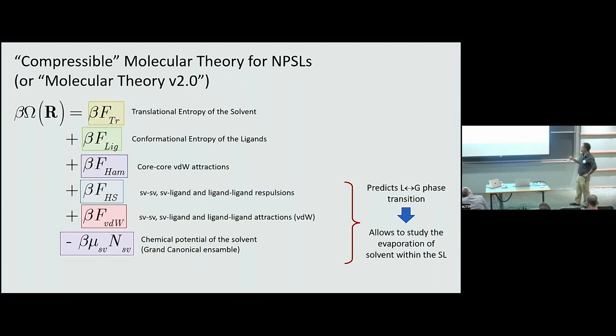for the attractions. And then because now we want to be able to tune the amount of solvent in the system, we need some handle to do that. So instead of using a canonical ensemble for the free energy, we're using a grand canonical ensemble, and we have this term. This is the chemical potential of the solvent, so we can tune that up and down, and with that control the amount of solvent in the system.